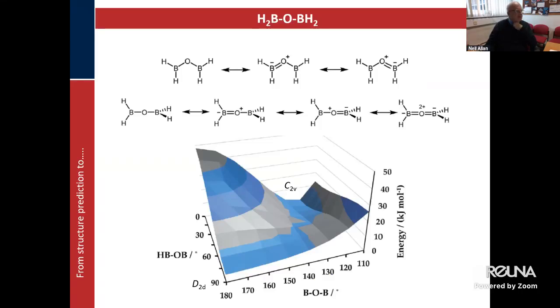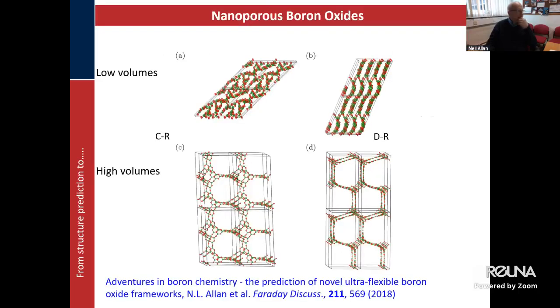But to extend that to the solid state, as we did, we managed to say that there were a lot of structures that you could build up for boron and oxygen. And they would have a very flat energy versus volume curve. Very flat indeed. More characteristic of those associated with MOFs, or metal organic frameworks, which are so fashionable these days. But of course, here there is no organic molecule at all.